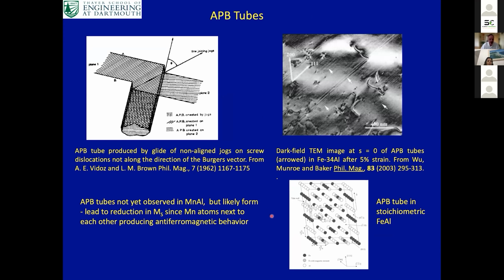So antiphase boundary tubes were first suggested in 1962 by Vidoz and Brown, and these are produced when you have pairs of APB-coupled dislocations gliding, and they intersect another pair of APB-coupled dislocations, such that jogs are produced on those gliding dislocations and no longer line. So as the dislocation moves forward, it then drags out this APB tube behind it.